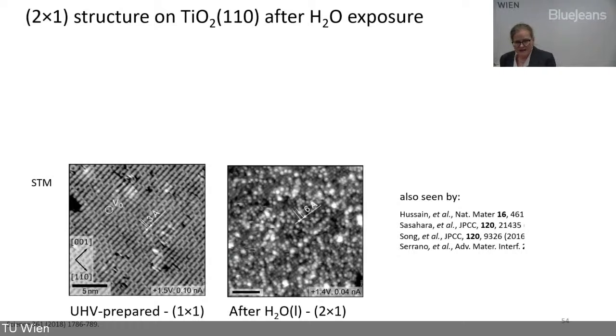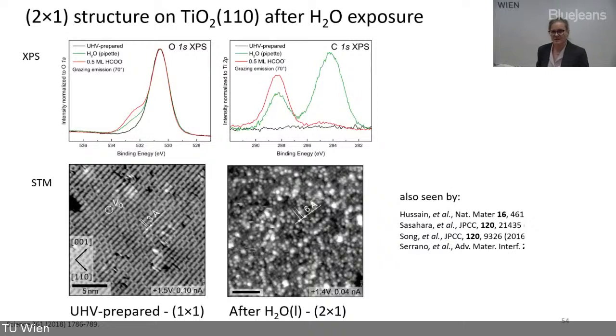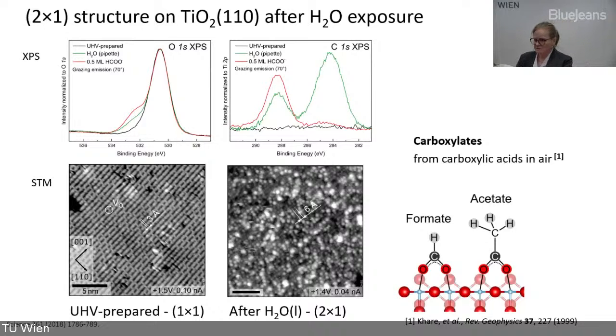In the end, what happened was that even though Jan was very careful, the surface got dirty—and you see that in XPS. On the right-hand side is the carbon-1s spectrum of the clean surface after putting on the water with the pipette, and as a control experiment, one monolayer of formate. On the left, you see the oxygen 1s. It turns out that when you just put the surface in air, there are carboxylic acids in the air everywhere, and they adsorb on the surface to make formate and acetate, which adsorb in a bidentate fashion.